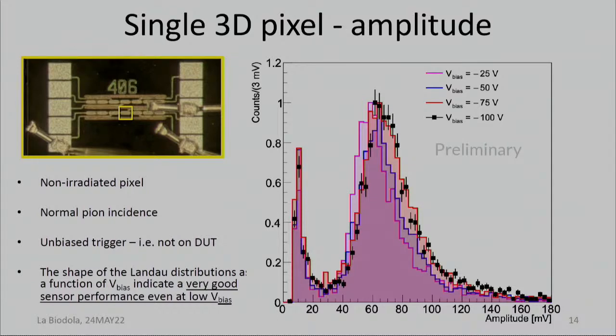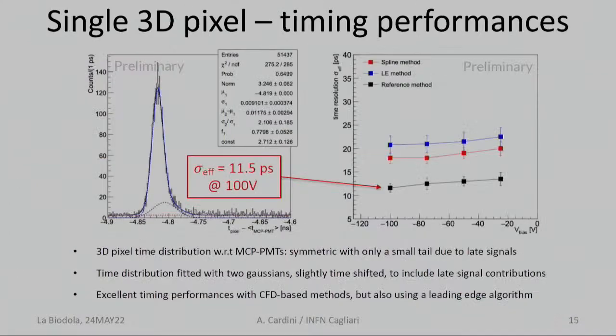We are not triggering all these signals. And these are the Landau amplitude distributions as a function of the voltage you apply on the sensor. You can see that even for low bias voltage, we have reasonable Landau distributions that do not change very much depending on the voltage. This is due to the very low voltage that those detectors are usually able to operate at.